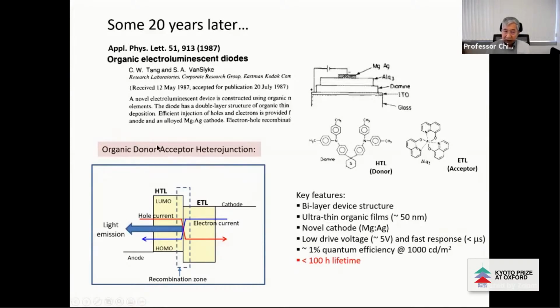Again, in this device, the donor acceptor heterojunction plays the key role. But in this case, it's very different. It doesn't require light absorption. You want to optimize for the light emission. And the junction itself is the one that plays the key role, because in this case, the electron gets blocked here and the hole gets blocked at the junction here. So the recombination is confined at this interface. And therefore, high efficiency can be achieved by eliminating some of the recombination at the electrodes.